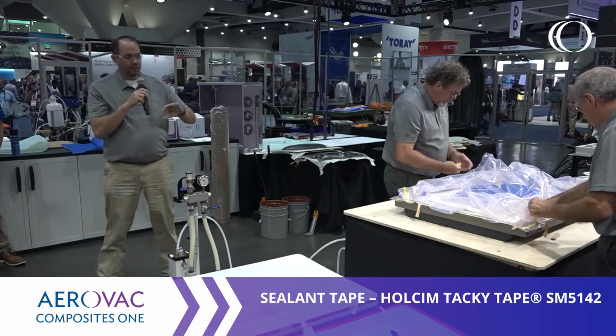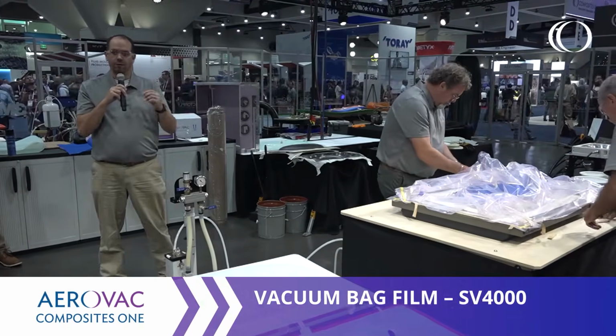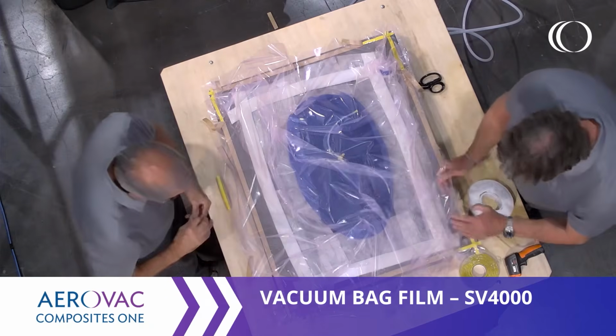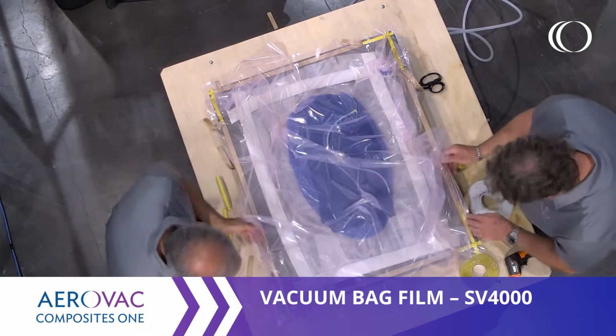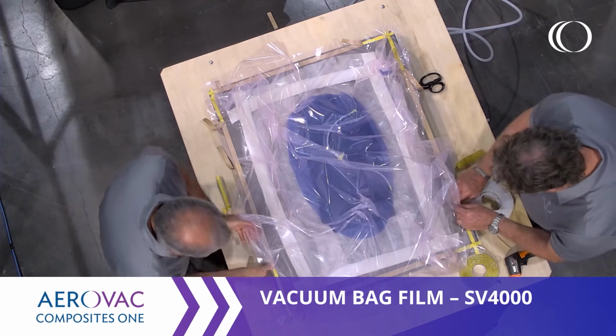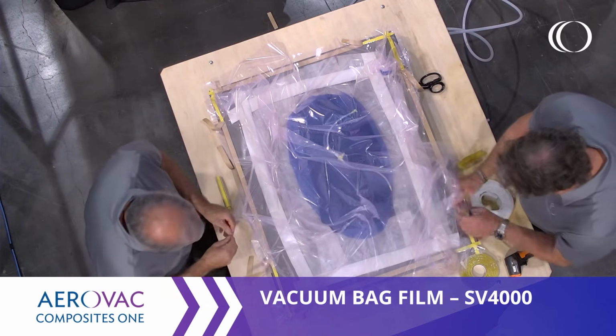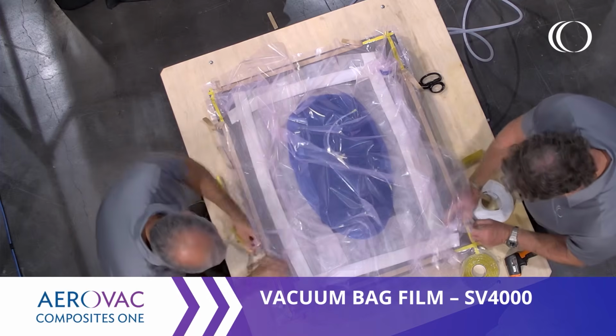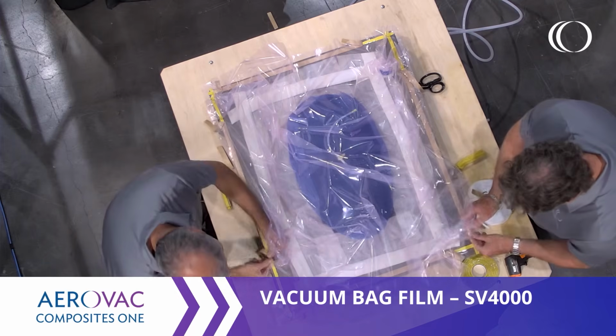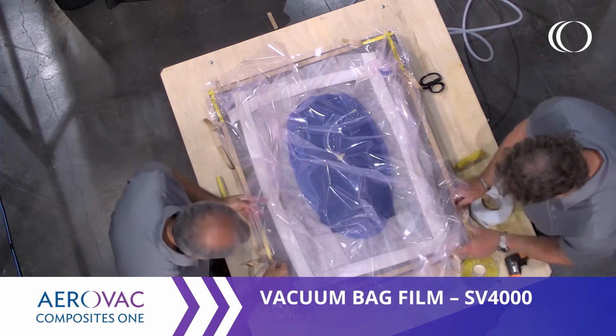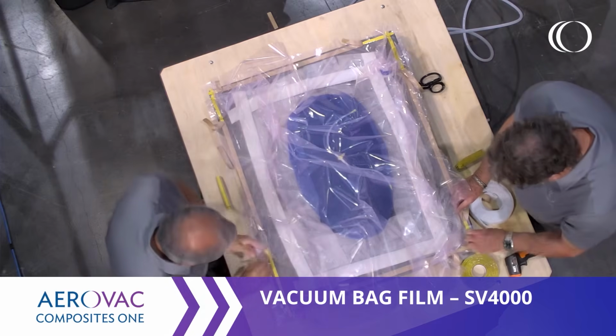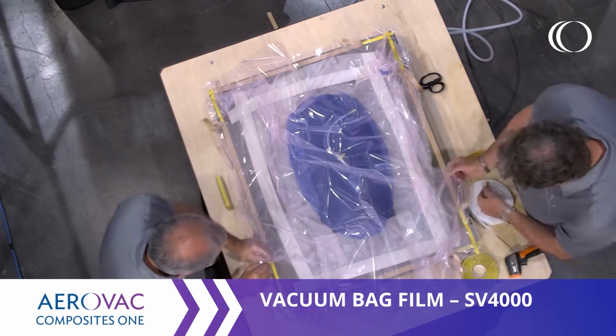And then they're encapsulating all of that with Stretchlon 4000, which is a co-blended nylon film, good to 400, a little over 400F, and it has a really high elongation. It's a fantastic vacuum film for major cure processes: oven, autoclave, and obviously infusion.